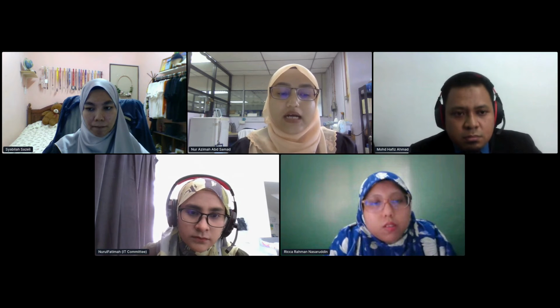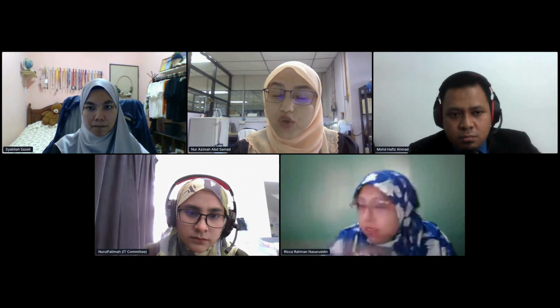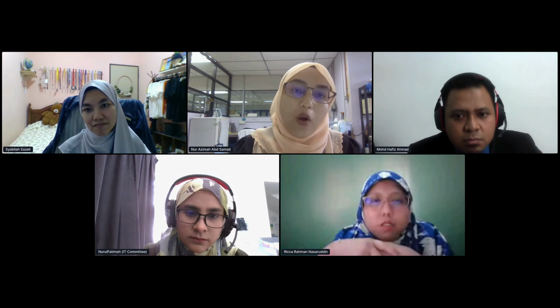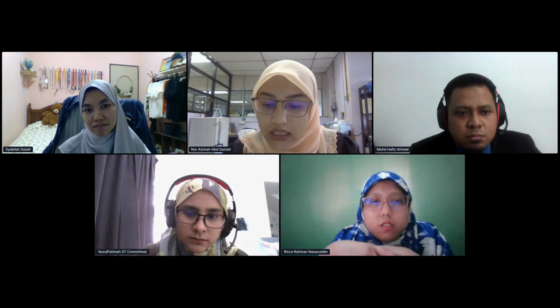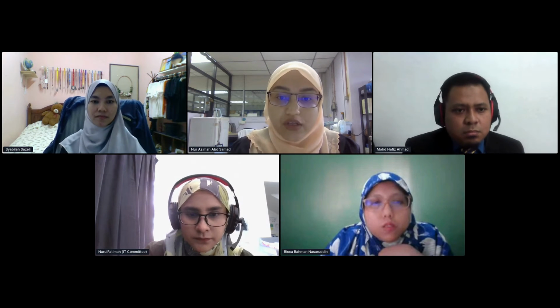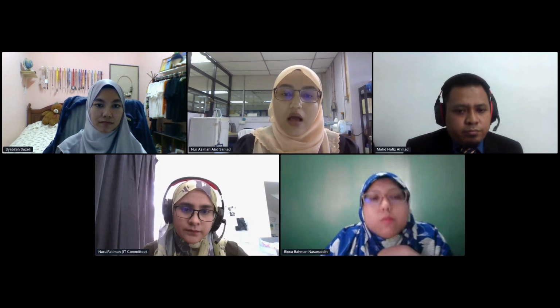Okay, from what I can tell you from the band gap itself, the titanium band gap is around 3.2 electron volts, while the zinc oxide is 3.37 electron volts. But after we combine them, it will produce 2.85. So it will improve the movement of the electron, and also from the photocatalytic activities, the percentage of degradation increases in the titanium zinc oxide heterojunction as compared to the zinc oxide and also titanium itself.